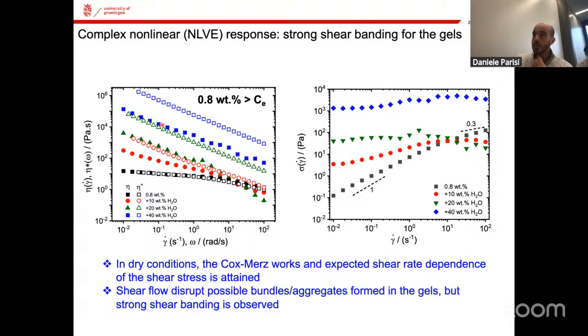When we plot the stress as a function of the shear deformation for the dry solution, everything follows what we expect from polymer physics. So in the linear regime, stress and deformation are linearly dependent. And then at some point, when the nonlinear regime is attained, we have a much weaker dependence of the stress on the deformation rate. But for the gels, something very strange happens: the stress doesn't really change with the deformation rate. It seems to be constant.